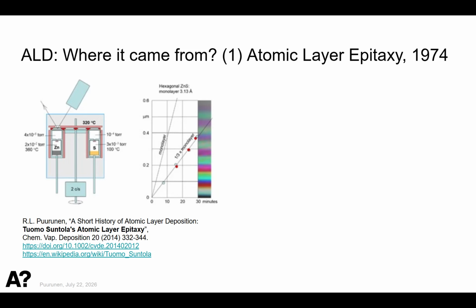substrates. He developed a reactor where he had a rotating system where the glass substrate was rotated on top of zinc and sulfur reactant areas. They were heated to quite high temperatures, zinc to over 300 degrees and sulfur to 100 degrees to get sufficient vapor pressure. And this glass substrate was rotated 2 cycles per second through those reactant sources.